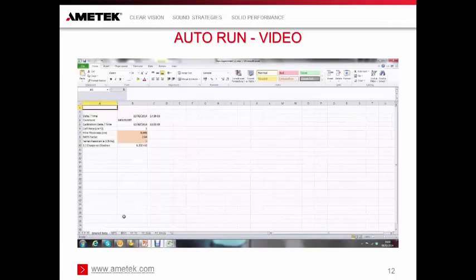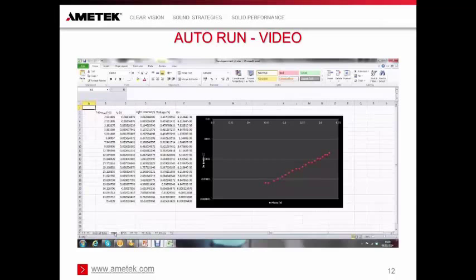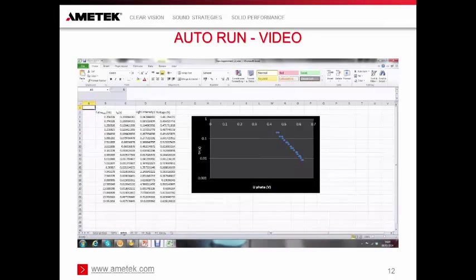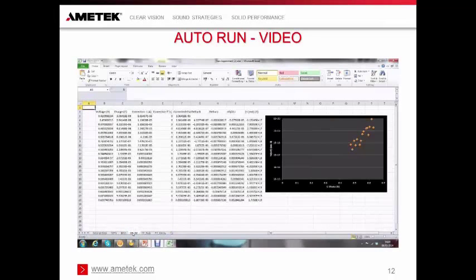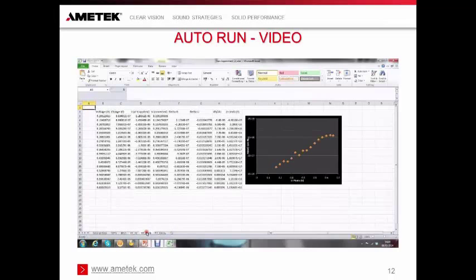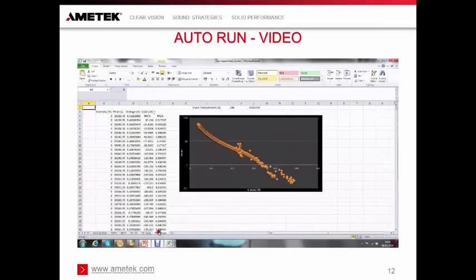And the data set has been analyzed. This is the full data set for the IMPS, where we've characterized the diffusion coefficient as a function of voltage. This is the IMPS, electron lifetime. This is charge extraction, charge extraction dark, and analysis of PV decay. Fully automated. That was a real-time experiment.